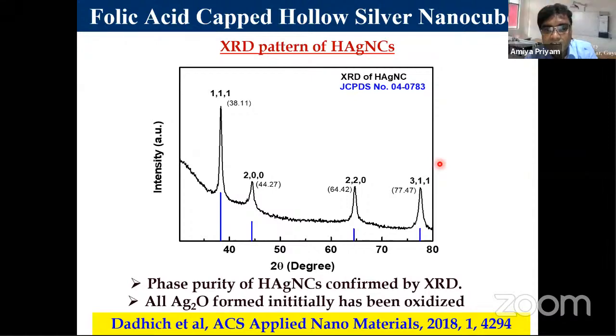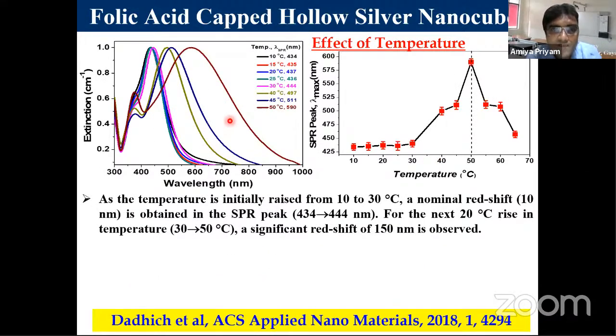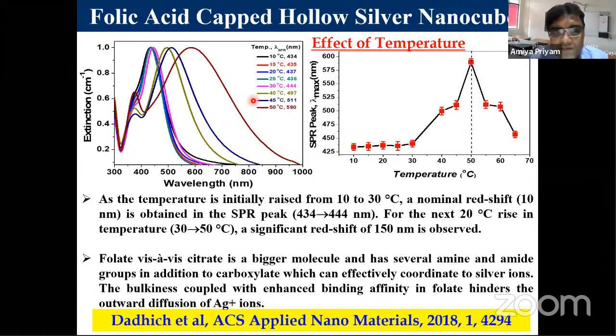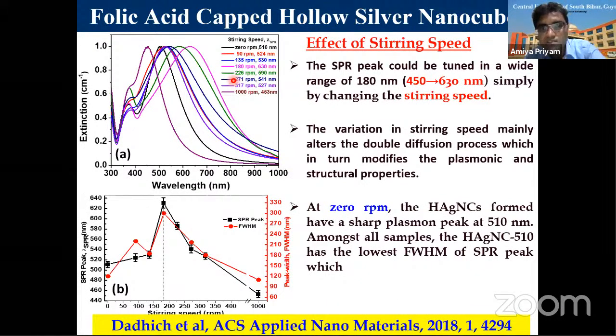This is the X-ray diffraction, which shows phase purity, and this is the tunability that we have got, which I was talking about ultimately. By changing the temperature and stirring speed, we are able to tune it up to 630 nanometers by varying the conditions as shown over here. By temperature, 50 degrees Celsius was found to be the best. It was a big chain of experiments, actually, which led to identification of a suitable ratio of reducing agent to silver ions, because it is not easy to get the right kind of hollow structures in one shot. You have to optimize things.